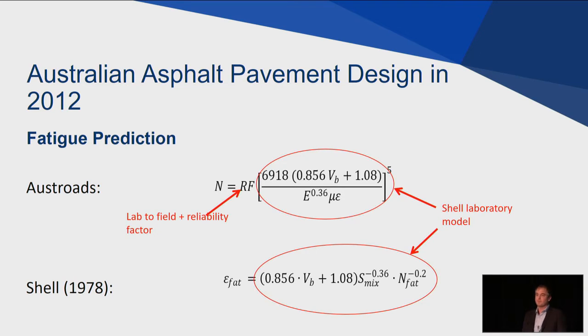And when it comes to asphalt fatigue prediction, many people wouldn't like to admit this, but what was in the Austroads guide was basically just the Shell laboratory model, which was developed for 12 mixes in the 1970s, tested in laboratories by Shell in Europe. And that model was used in the Austroads design method unchanged. The only thing that's in there is a laboratory to field shift factor, which for the major roads was 1. So basically we were predicting that the fatigue performance in the field was equal to the fatigue performance in the laboratory of a beam. So that's as it stood in 2012.